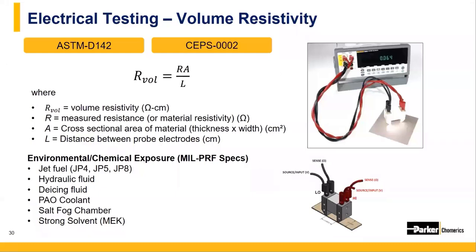With the relative simplicity of the volume resistivity test, it's often conducted before and after environmental and chemical exposure tests. Coated parts can be run through all kinds of fluid exposure and then tested for volume resistivity to ensure that the coating will maintain EMI shielding or grounding performance after long-term exposure in harsh environments. Examples of some of these fluids include jet fuels of various grades, hydraulic fluids, PAO coolants, strong solvents such as MEK, as well as long-term salt fog chamber exposure.